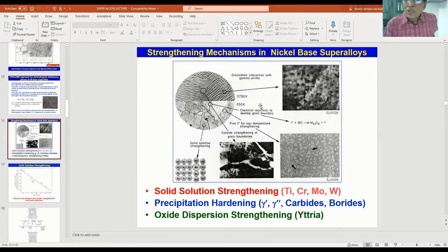Now, some of these carbides I talked to you about, titanium carbide, titanium molybdenum carbide, are the ones which will interact with the matrix at elevated temperature, and they decompose into chromium carbide in the matrix, and gamma prime forms, and they contribute to the strength. But what we have to see is that we have to reduce the MC type of carbides. Otherwise, this type of reaction will be taking place, and you will have phase instability in the material. So, in case of nickel-based superalloys, we have solid solution strengthening coming from some elements, precipitation hardening of the matrix coming from some elements, and then the grain boundary strengthening coming from the carbides and borides, and then